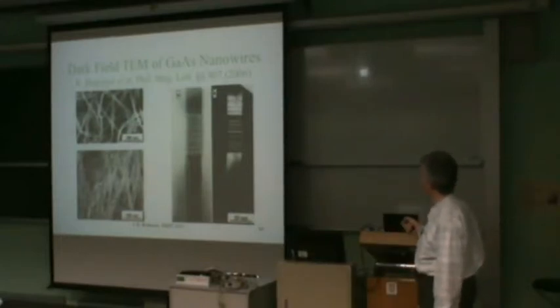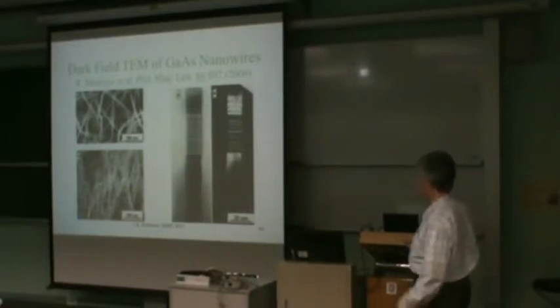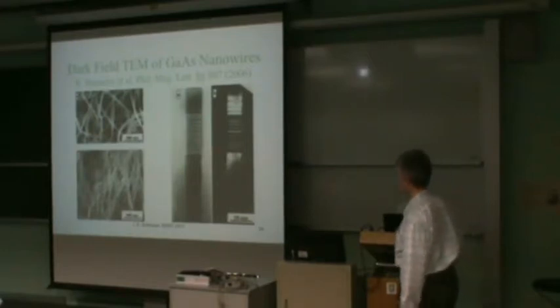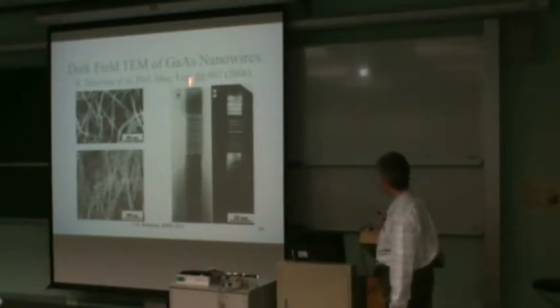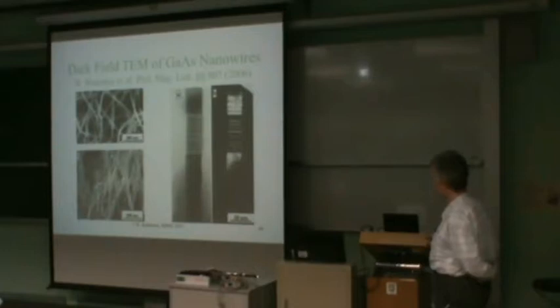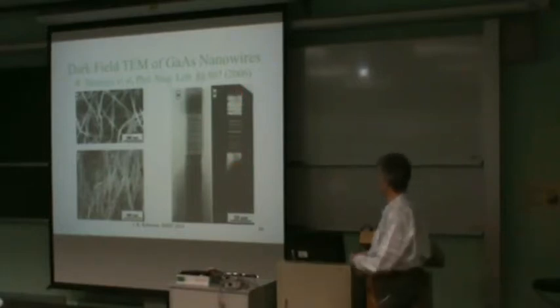And here's another example showing a slightly better TEM image, where if you look at gallium arsenide nanowires, you can see that you get both the light-dark contrast. This corresponds to stacking faults. These are imaged by dark field TEM, where you look at just one Bragg peak, and that picks out just one of the 3 phase registries of the material, and it looks light and dark according to whether you have the reverse stacking sequence or not, and then the stacking fault appears as a local light-dark contrast. If you go 60 degrees away, you can measure the opposite contrast from the same wire. So you can do it rather nicely with TEM and see these stacking fault sequences.